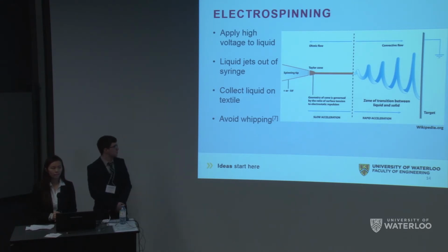So in order to avoid this whipping effect, we would move our substrate closer to the syringe, thereby avoiding the effect before it starts. So although this was the solution that we felt would be able to meet our goals, we were unable to pursue this method due to the fact that we did not have the necessary equipment. With that in mind, we chose to focus our attention on achieving our goals, doing what things we could through our available time.